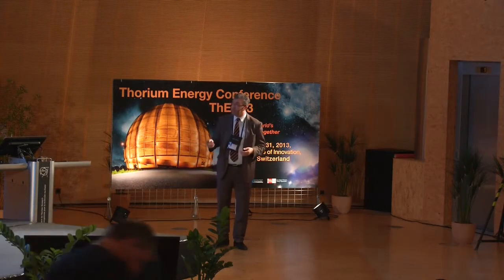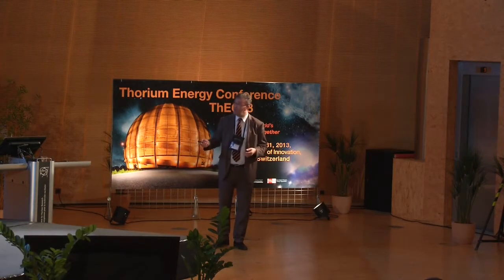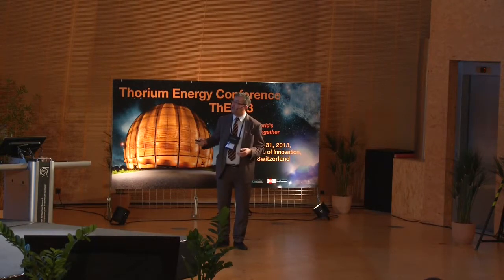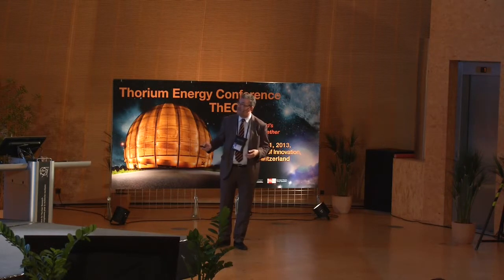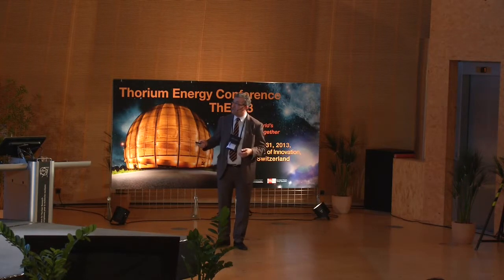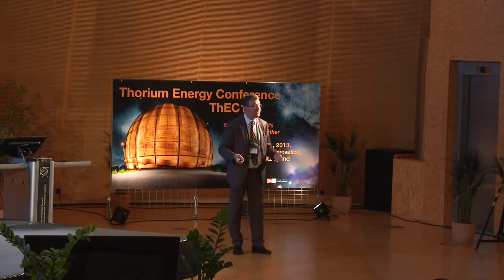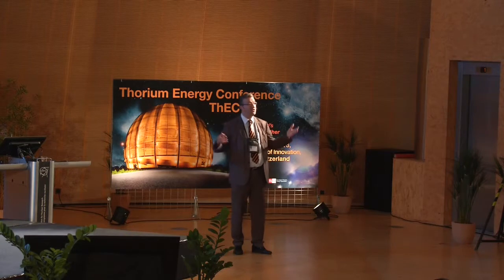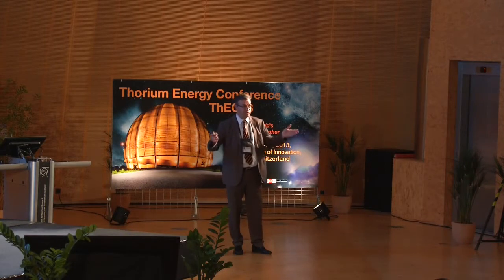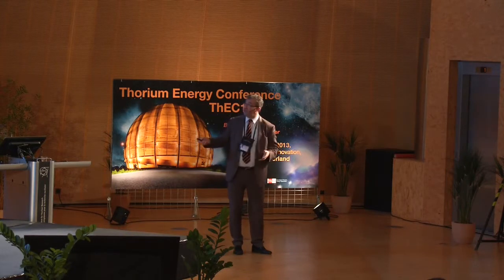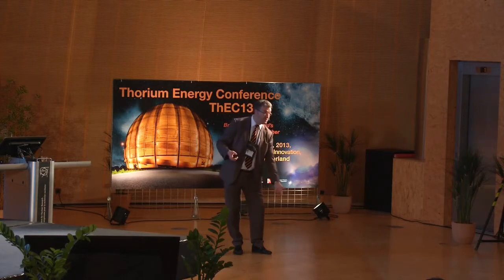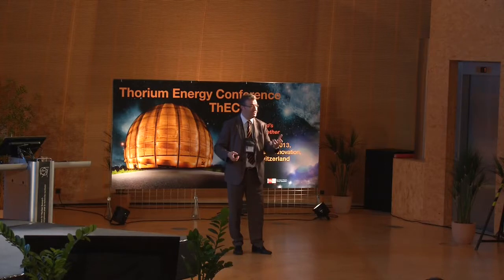So the core is made of hexagonal assemblies. You see, for 0.95 as a K effective, we can reach that with 69 fuel assemblies. You see those green dots, these are the control rods. As I said, we were asked to be also able to operate in critical. We put control rods, and the control rods are inserted from underneath, just like the fuel, we are loading the fuel from underneath.